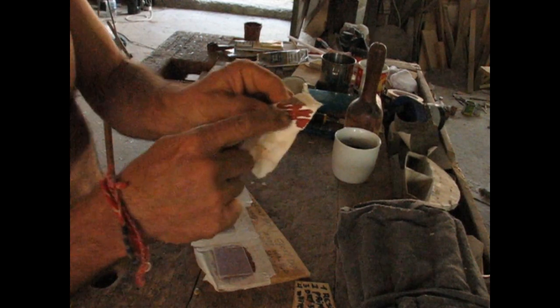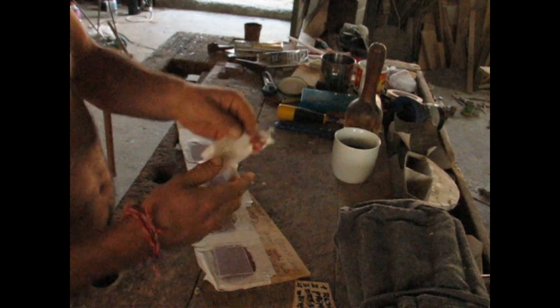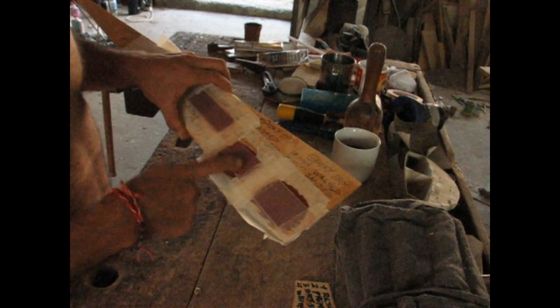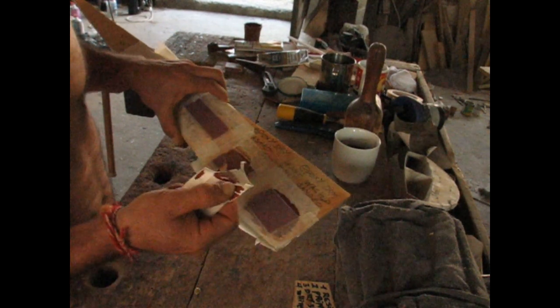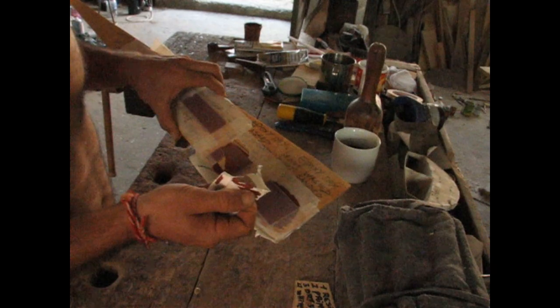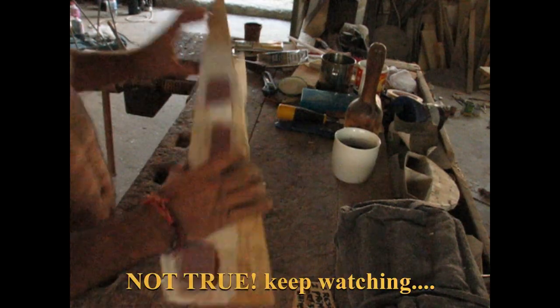On the second one — epoxy only washed with acetone, not sanded — the paint has pulled off. The glossy epoxy couldn't adhere to the glossy epoxy resin. Full pieces of paint have come off. Let's go to the third one: sanded, washed, and sanded.